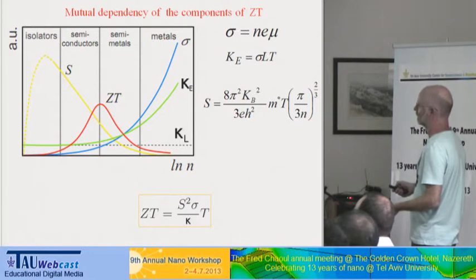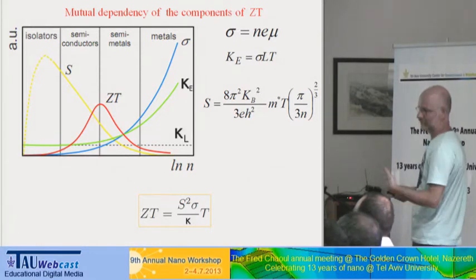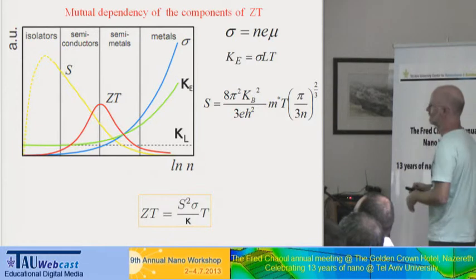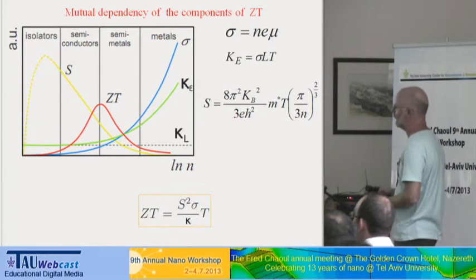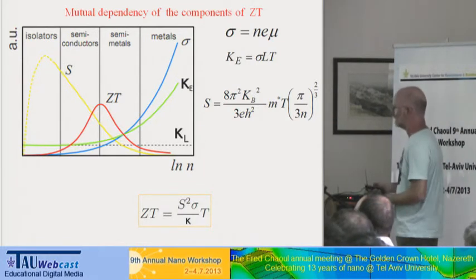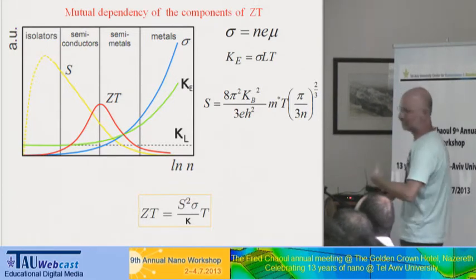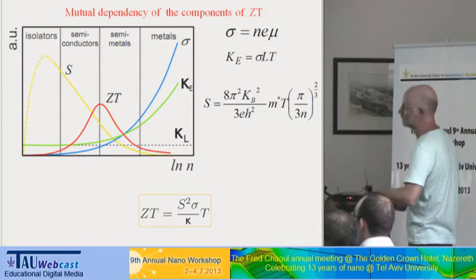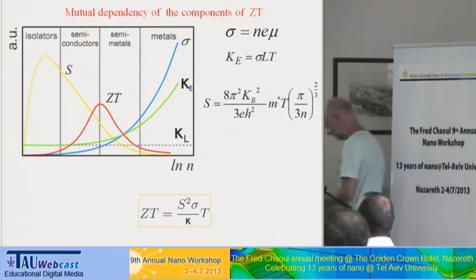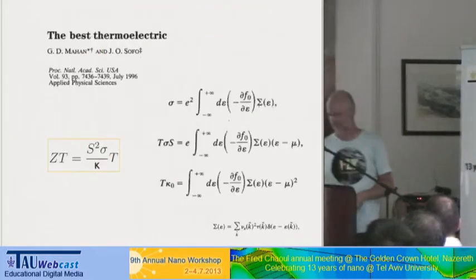The lattice thermal conductivity is the same, it is by the phonon, so it's roughly the same, and the Seebeck is going down. And since the ZT is what you see here, the maximum ZT is somewhere around here, so most of the materials, everybody is using either semi-metals or semiconductors in order to have really efficient thermoelectric coolers.